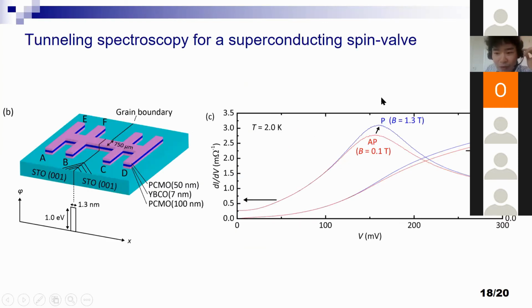And we can also observe this effect at a temperature far below TC. And we did density of states analysis. And we used grain boundary substrates because we don't have helium-ion focused ion beam machine. And basically it's sandwiched by thick two ferromagnets, and it's difficult to use, for example, STM to measure the density of states of superconductor inside a superconducting spin valve. So probably this grain boundary method is the only method to measure density of states of this kind of structure.